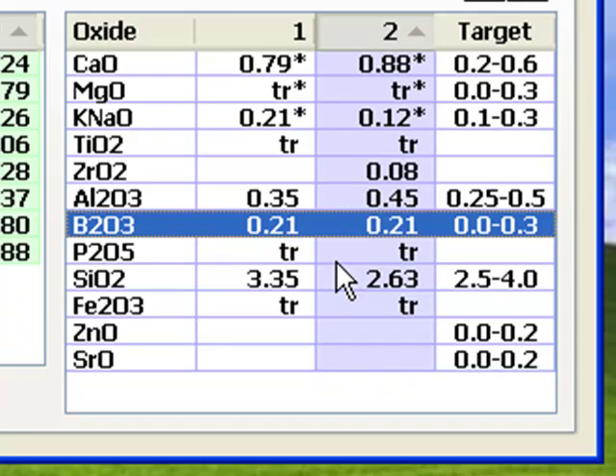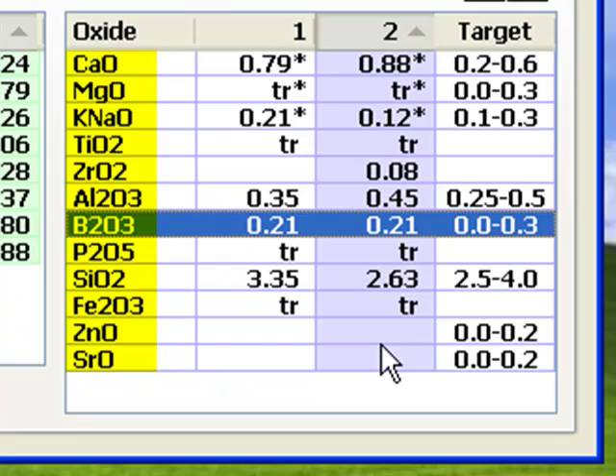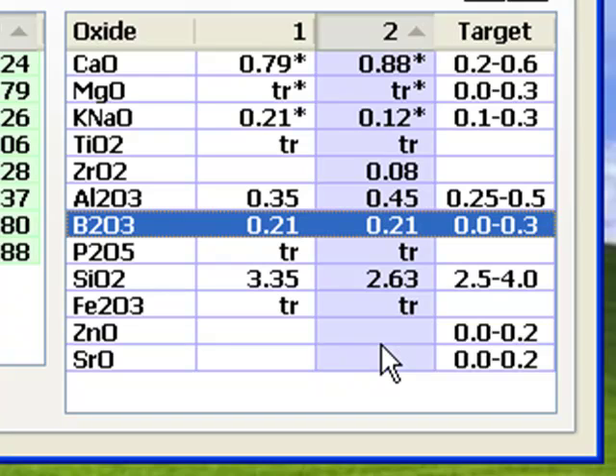My initial goal was appearance and glaze fit, but it would be easy to add a coloring oxide like cobalt and then do a vinegar leaching test as an initial indicator. But the solution still will be a matter of understanding oxides and their interplay. You might think I'm taking a cavalier attitude toward the limits, but remember that limit formulas are about what melts well, not what does not leach. If I exceed a target and get good melting, that's great. Glazes within limits are less likely to leach, but those outside can also be durable. Also, mattes are considered special purpose glazes, so don't expect them to have typical chemistries.